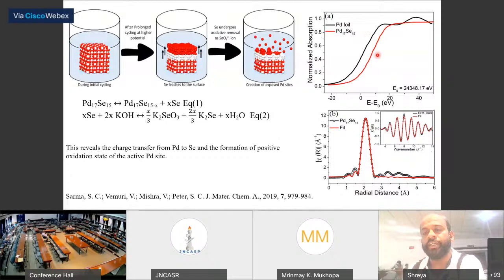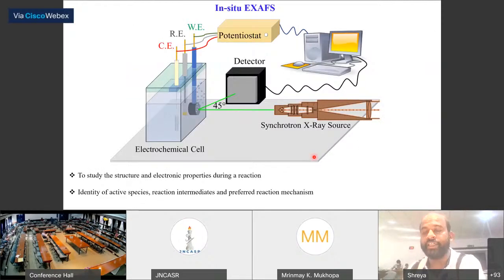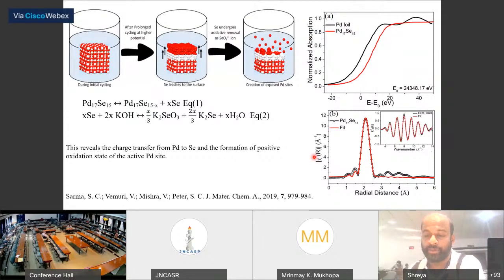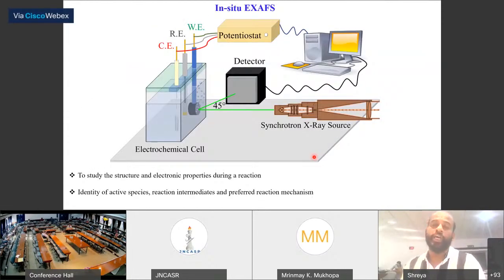in absorption energy, and you can see that this is the selenium edge, and there is a formation of positive oxidation state in the active sites of the palladium. This we have also done with the palladium 17 EXAFS data. There is not much change in the coordination environment. We have also done in situ XAFS studies in beamline P64, and this is a setup we have developed there during the experiment.